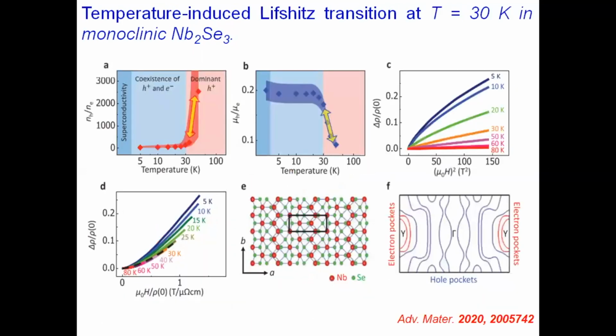So here there are two experiments they have investigated extensively. One is magnetoresistance, another one is Hall resistance. Magnetoresistance will give you a claim about the Lifshitz transition, I suppose you understood it. It is the opening of the Fermi surface, from a closed Fermi surface to an open Fermi surface. You would have encountered this Lifshitz transition in Weyl semimetals. Often you would be seeing it in the literature.